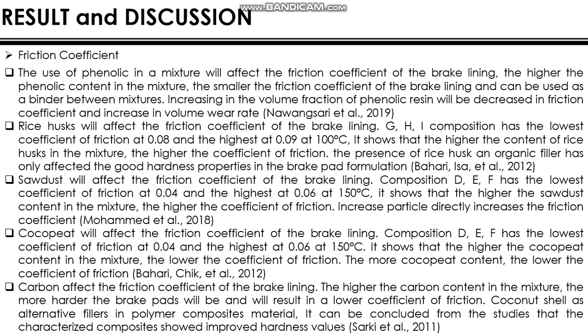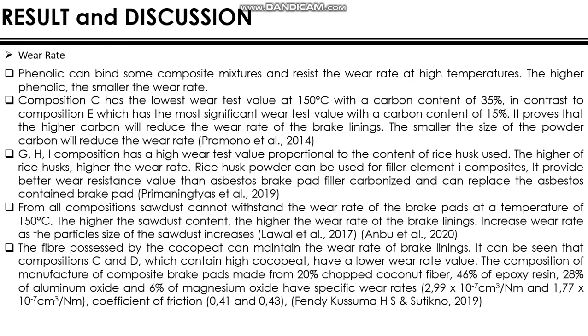Carbon affects the friction coefficient of the brake lining. The higher the carbon content in the mixture, the harder the brake pad will be and will result in a lower coefficient of friction. Wear rate. Phenolic combines the composite mixture and reduces the wear rate at high temperature. The higher the phenolic, the smaller the wear rate. Composition C has the lowest wear rate value at 150 degrees Celsius with a carbon content of 35%. In contrast to composition E, which has the highest wear rate value with a carbon content of 15%. It proves the higher carbon will reduce the wear rate of the brake lining.